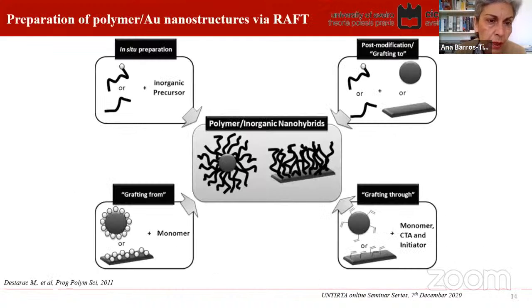So using RAFT, we can then prepare gold-based nanostructures following a variety of strategies. We can use in situ preparation, we can use post-modification, which is also referred to as grafting to. We can prepare these hybrid nanostructures using the grafting from and also the grafting through. Now, these may sound all a bit strange or all the same, but it's not exactly the same. And in fact, we assessed this variety of strategies, and in the end chose, I can tell you in advance, the grafting from strategy. But of course, this is sort of obvious when you have tested and know the final results.